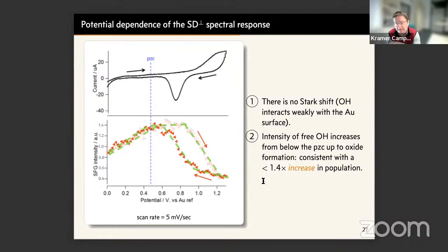If you do that, several things become immediately clear. The first is that there is no Stark shift. As you vary potential, the spectral feature doesn't shift. This is consistent with the single donor perpendicular species, and with the frequencies at which we're measuring, which suggest a really weakly interacting OH.